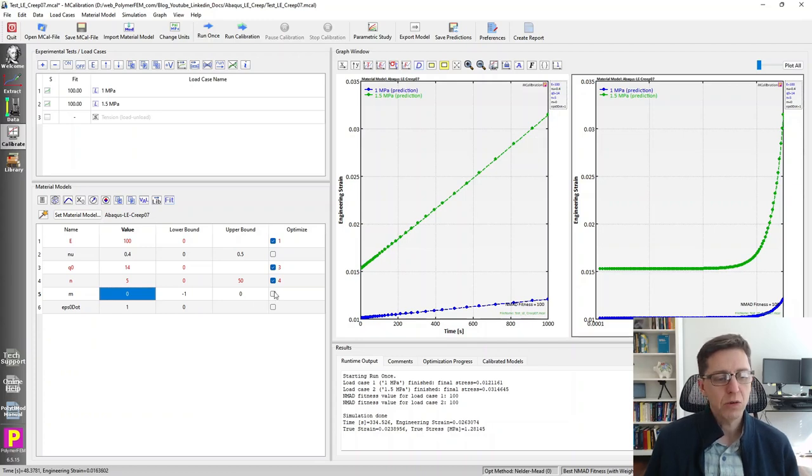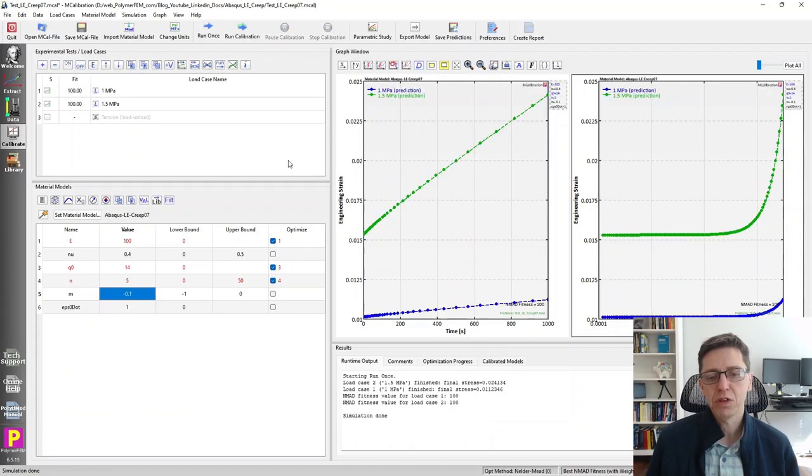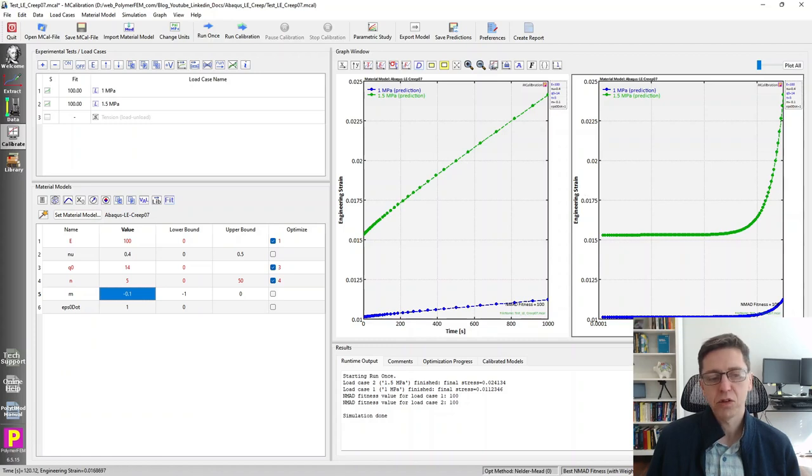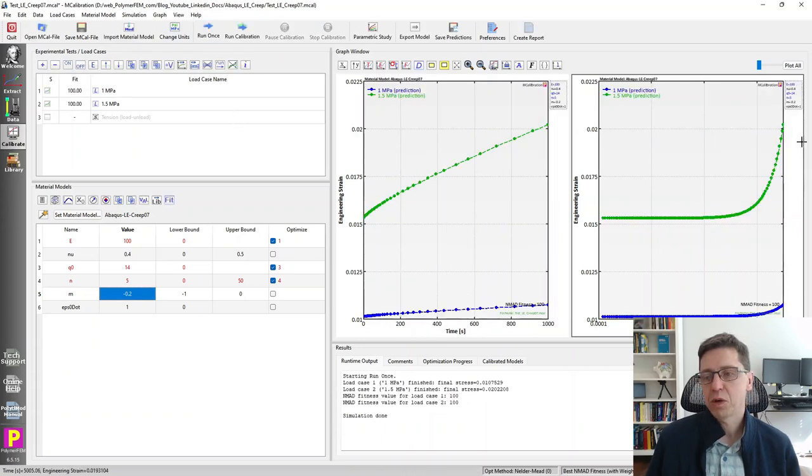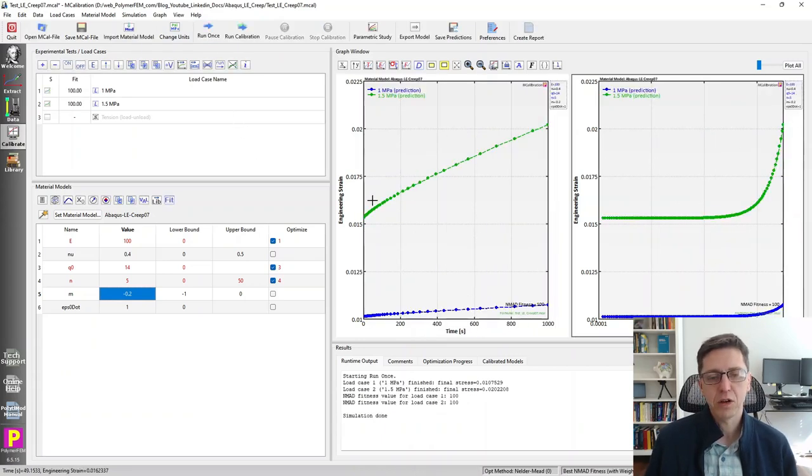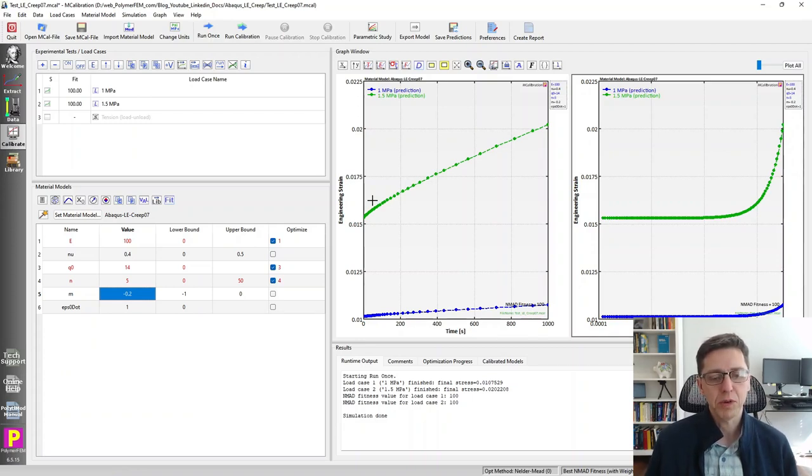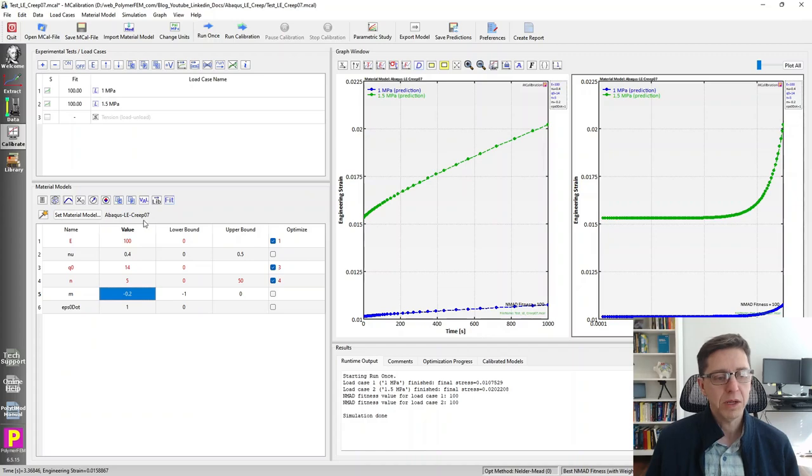What you can do is with the M parameter here, if you set it to be a little bit negative and you run this again, we will see that it actually changes the slope here. It makes it flow a little faster initially, and then it slows down. So you can tweak the creep response a bit with the M parameter in this model. It drags this down, less accelerating at larger strains. We have, in essence, a strain-dependent creep model. So that's pretty simple. This is a model that I actually like of these different creep models that are available, the strain-dependent power model.